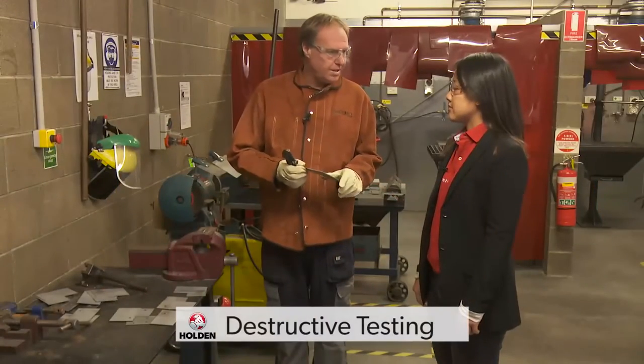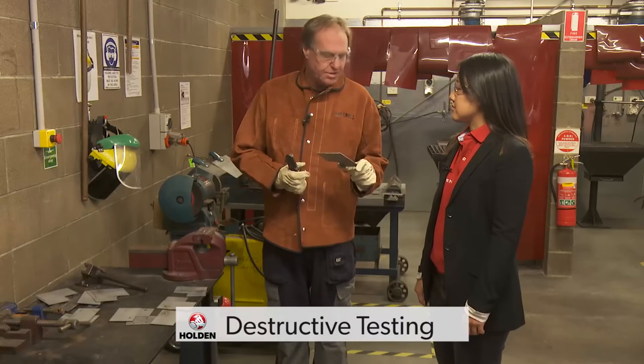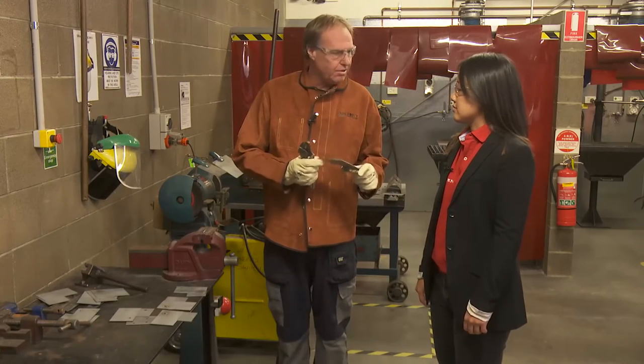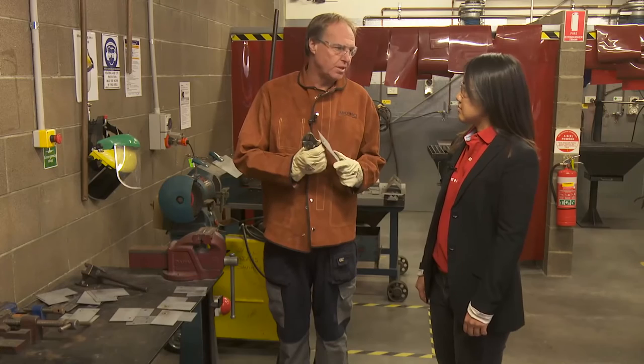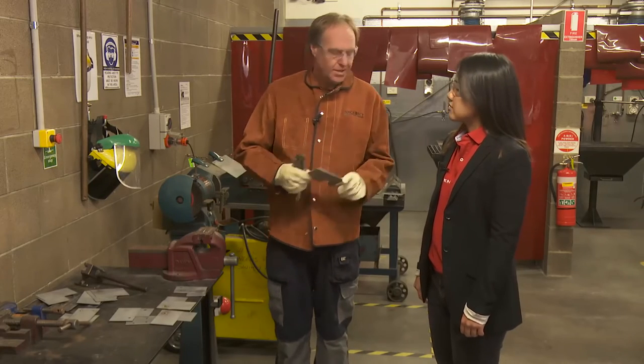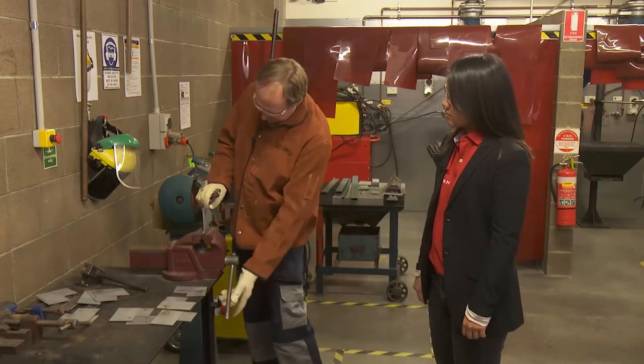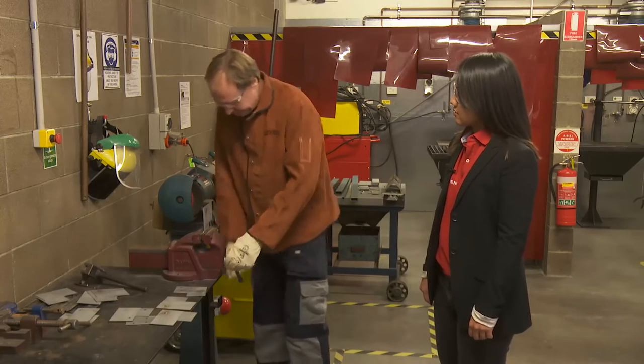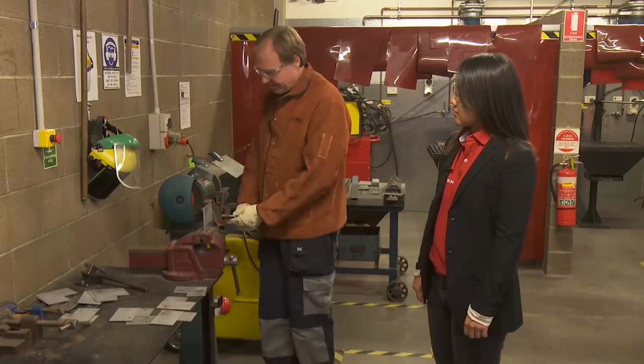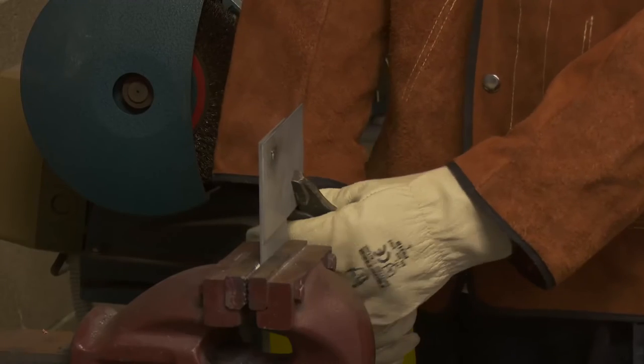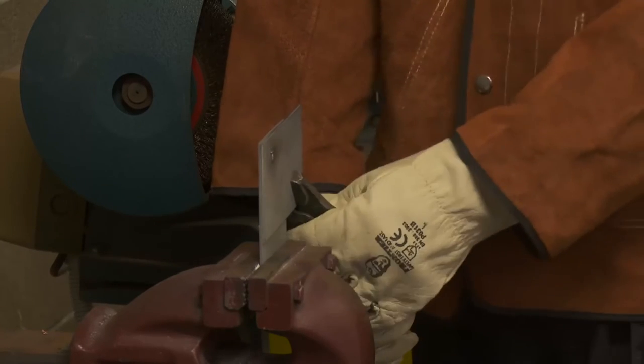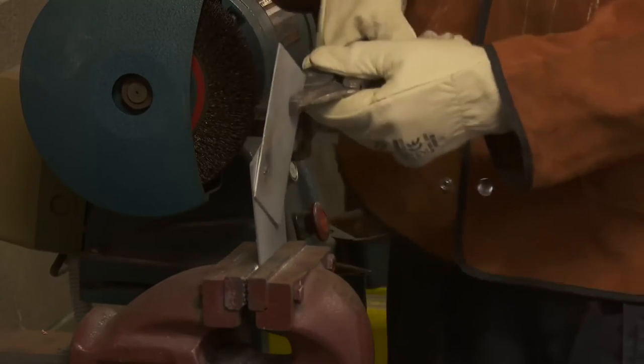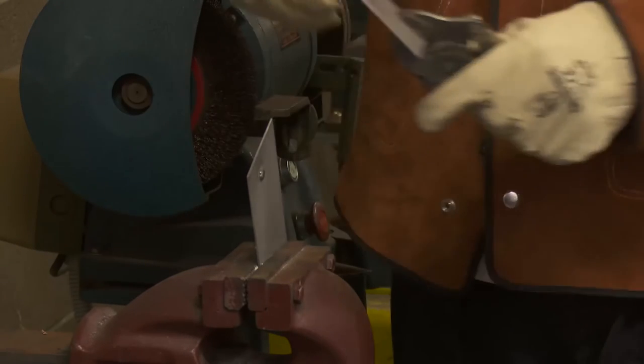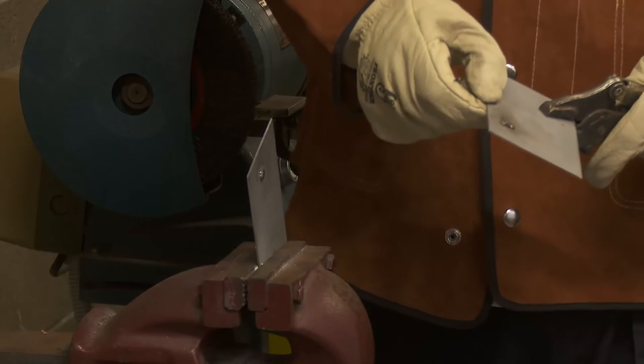Okay, Victoria, we've done these welds. I'll show you how we do destructive tests. What we're testing for is actually the core strength of the weld. That's why we twist them. So I put them in the vise. Once we're in the vise, we twist it up and around, and you'll see that one there is actually pulled straight out of the top plate through the hole.